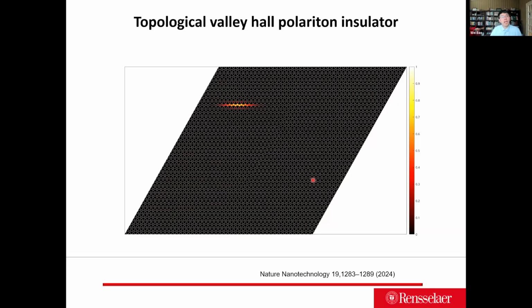Think about our experiment has 100 keV E-beam lithography directly on top, nothing damaged. Think about we have oxygen plasma treatment before we coat the PMMA on top for 2 minutes. So I think it's really a robust material. The only thing that is a little bit annoying is you have to have a laser that excites them with 370 nanometer wavelengths. And then the growth, compared with the cesium lead bromide, is a little bit non-trivial.